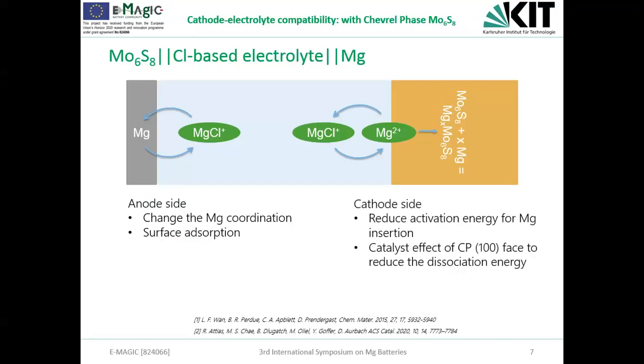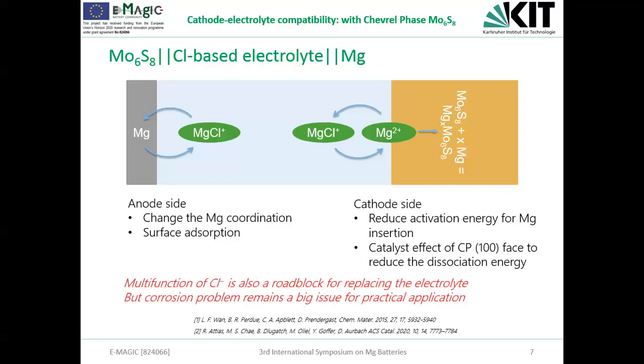And at the cathode side, the chlorine could also reduce the activation energy for magnesium insertion by changing the solvation. Also, for the Chevrel phase, the surface molybdenum atoms have a certain catalytic effect on the dissociation between magnesium and chlorine. So this further improves the insertion kinetics. So there's no doubt that the combination of the Chevrel phase with a chlorine-based electrolyte is successful, but the multifunction of chlorine also makes it difficult if we want to replace it with a chlorine-free electrolyte system.